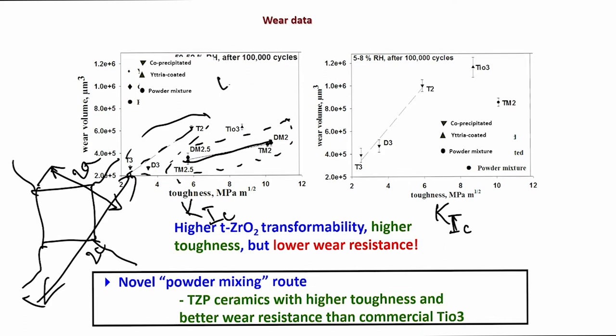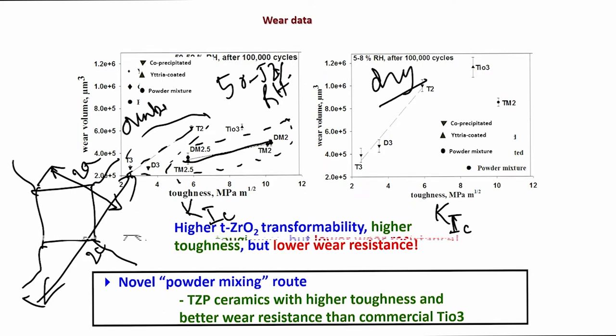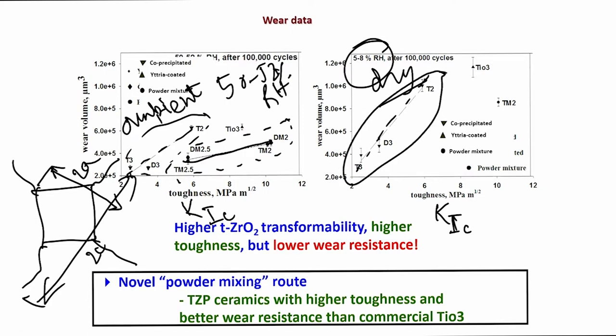This is not only true for 50 to 52% RH, that is relative humidity, that is ambient conditions, and this is under dry conditions. This is your ambient and this is your dry conditions. So, dry conditions again, 5 to 8% relative humidity, again you see that fracture toughness increases from T3, D3 to T2, that fracture toughness clearly increases, and that leads to an increase in the wear volume.